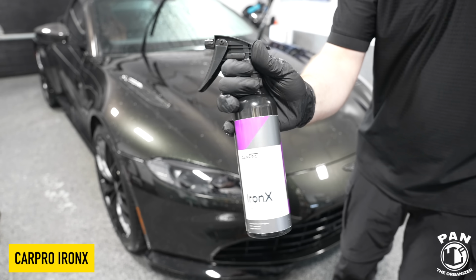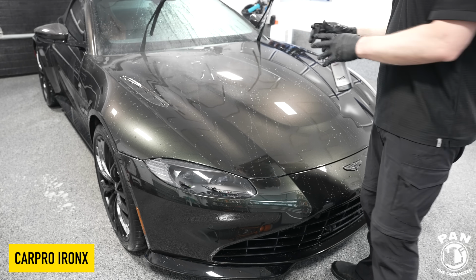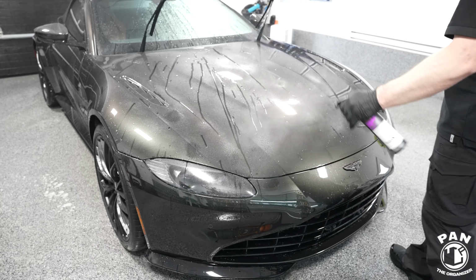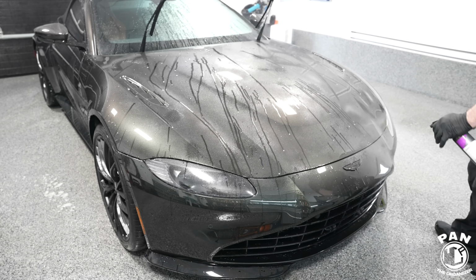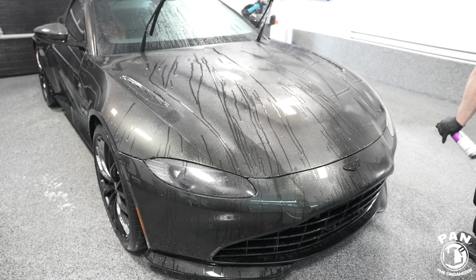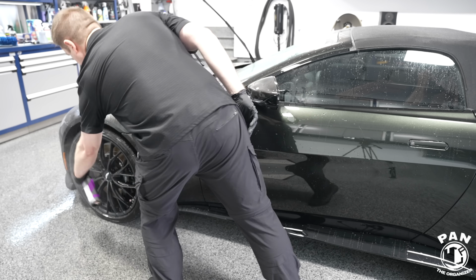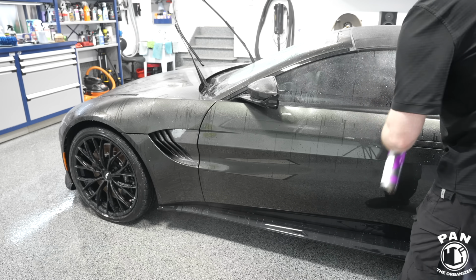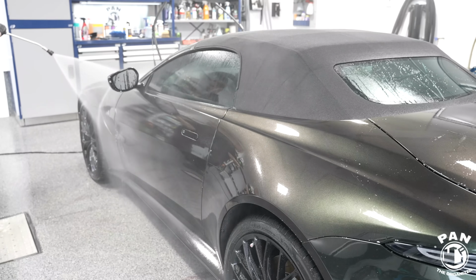If you look at the iron particles through a microscope, you would see that they have jagged edges. Those edges really encrust themselves deep in the clear coat and cling on. So when you use iron removers, it accelerates the oxidation process and rounds off or smoothens those edges, helping them be more soluble to flush them out with water afterwards. That exothermic chemical reaction from the iron remover really helps to change the shape of those iron particles. You flush them out. So when you're moving on to your clay stage afterwards, you have less contamination to remove. So I would do chemical decon first.